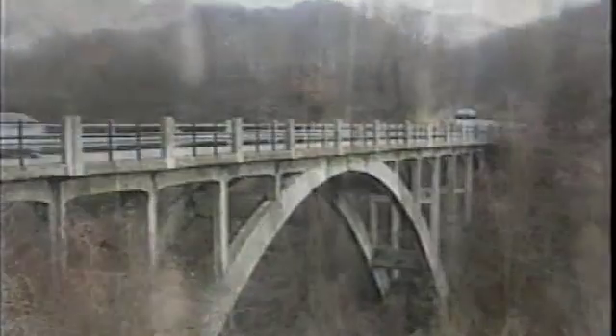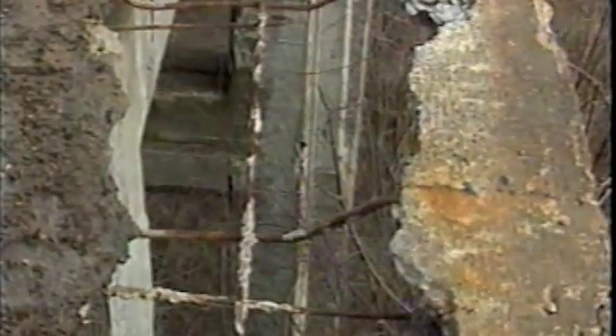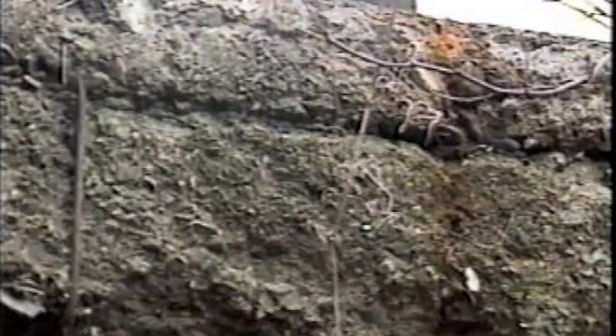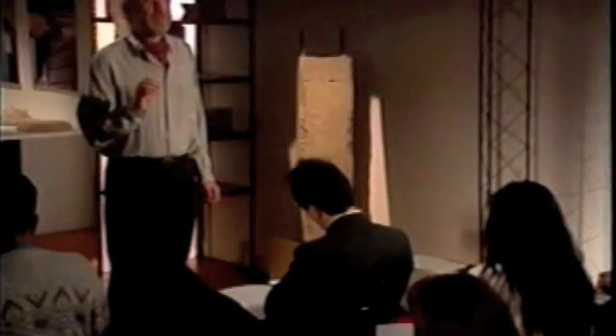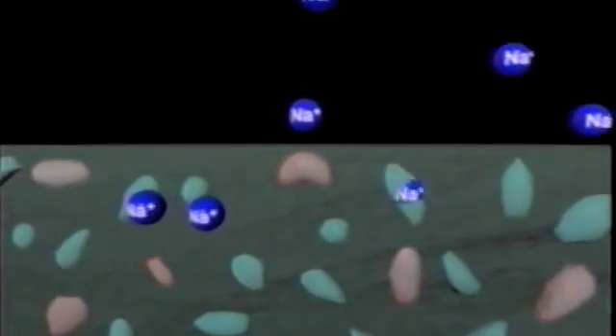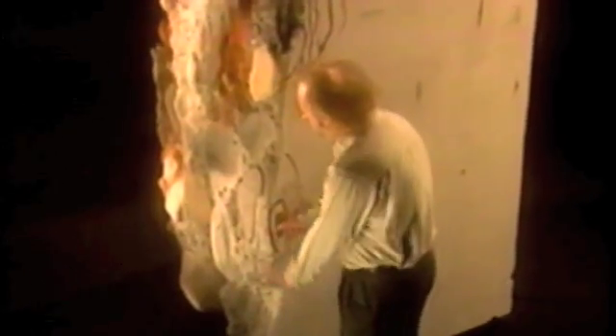The destructive action of low temperatures. Sodium chloride, on the other hand, is an aggressive agent. Sodium, already present in cement or penetrating from the outside, as we can see in the cartoon, reacts in particular with certain siliceous aggregates. In this case, too, there is expansion and cracking, above all in unprotected structures or those exposed to moisture.